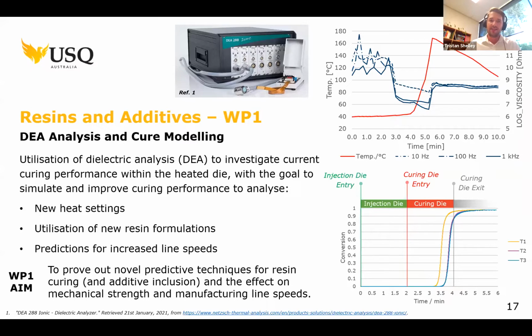And lastly, resins and additives, work package 1. As a big part of this work package, we're looking to dielectric analysis, or DEA, to investigate the curing performance within the curing die. Because the curing dies are sort of a bit of a black box. We don't really know what's happening. And DEA allows us to measure what's called the log ion viscosity, or ion viscosity. So the sensor sends a current through the resin, and the higher the ion viscosity, the higher the actual physical viscosity of the resin. So you get to a point at which the resin has cured.